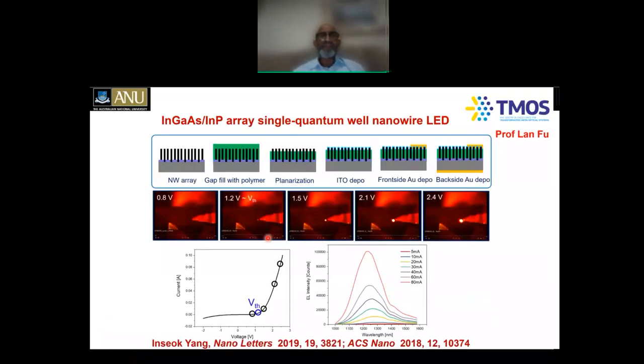Instead, before leaving, instead of making single nanowire LEDs, he's also created an array of nanowires by essentially, as I told you, the patterned structures. Then he fills the gap in these nanowires with a polymer material and selectively etches the polymer using plasma etching, exposes the tips of the nanowires, puts some indium tin oxide on the top, and a metal on the side and the bottom metal, so that you can inject current into these. You can see the IV characteristics showing diode-like behavior. As you inject more current, the electroluminescence intensity increases. In fact, you can see under the probe, very bright light in this case.